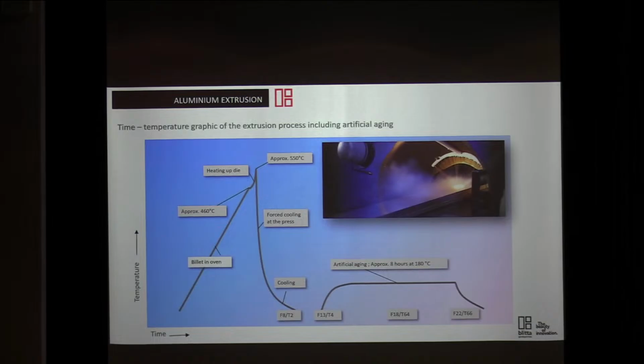As I said earlier, aluminium melts at 660 degrees centigrade. So we heat the billet in the oven to about 460 degrees. Then the billet goes in the container with the die. Then we heat it up a little bit further until 550 degrees. And then it's the mush state we can use for pressing the aluminium through the die. Then you cool it, and when it's ready, it has a tensile strength of T2. You can look it up in the norms. Normally, aluminium over a time period of 2 years will get to a tensile strength of T66. We don't have that time, so we do artificial aging. The profiles go in an oven for about 8 hours at 180 degrees. So we speed up the process a little bit.